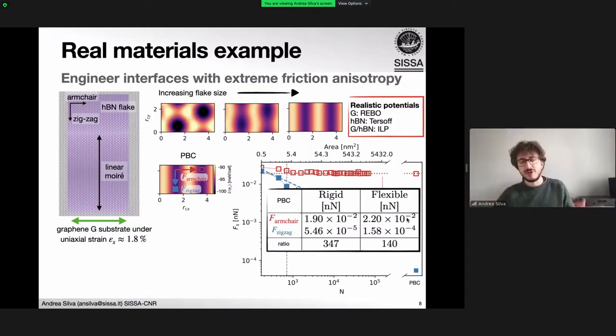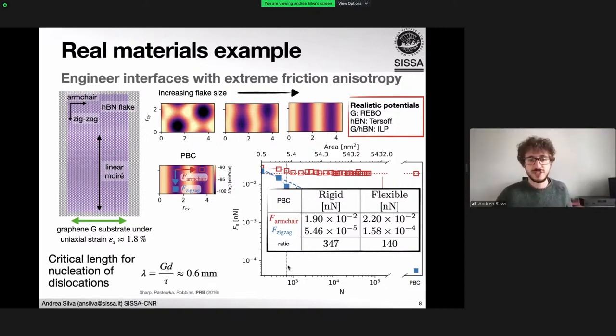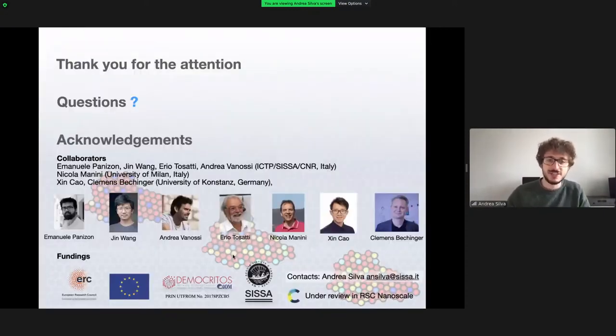And finally, you can also predict when elasticity will win over this, which for this case should be about 0.6 millimeter in linear size, according to the critical length estimated by Sharp in 2016. And with this, I just want to thank all the collaborators, and any questions we'll take after.